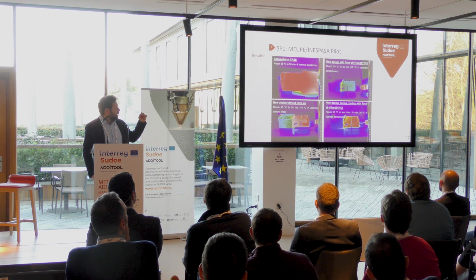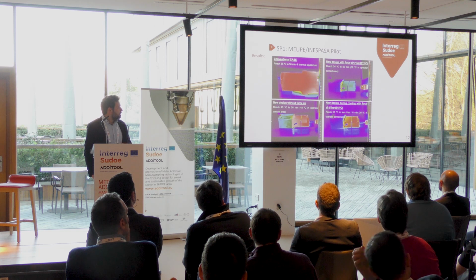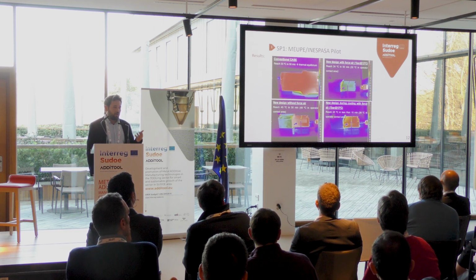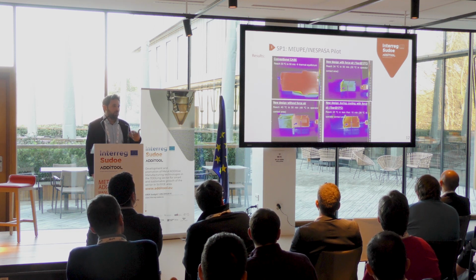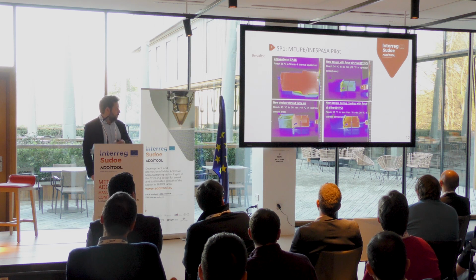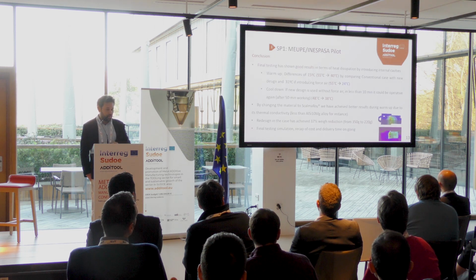But in the right top, you can see during 15 minutes working with air during operation, and the maximum temperature that we reached was 24 degrees. These results were really good for us, and it was also the expected outcome.